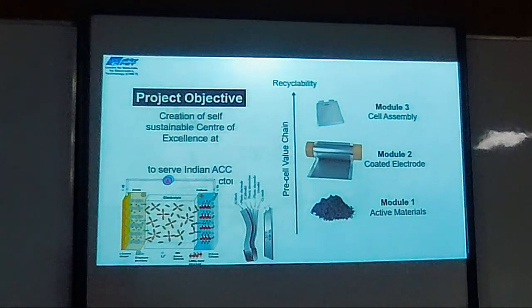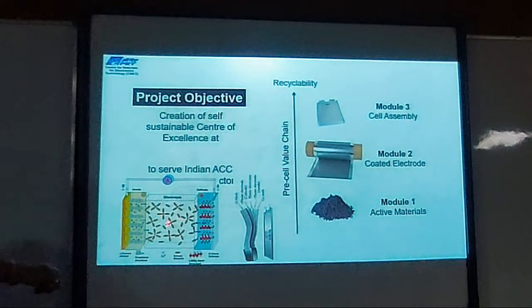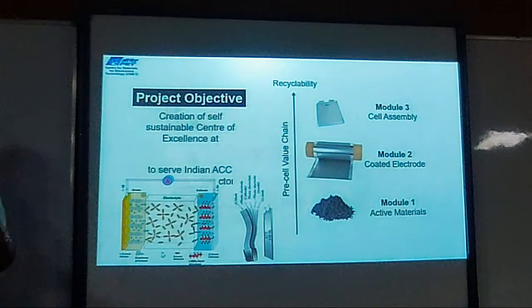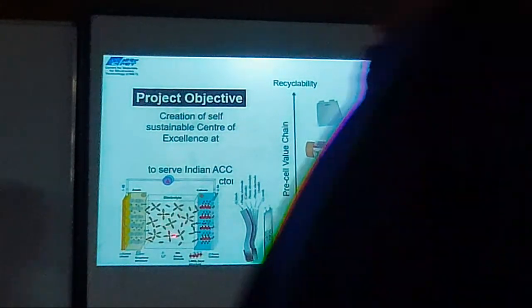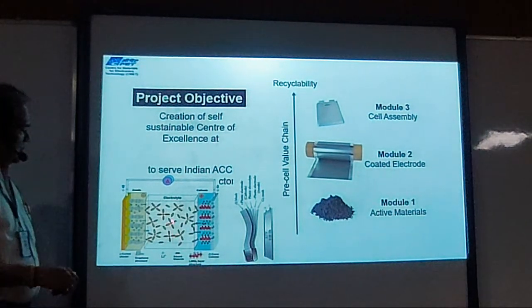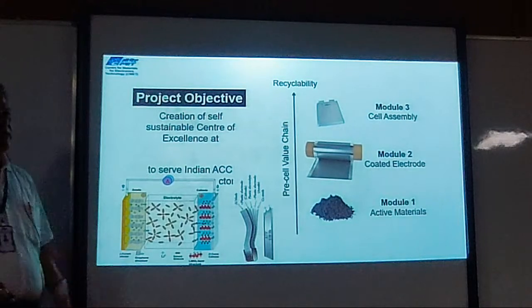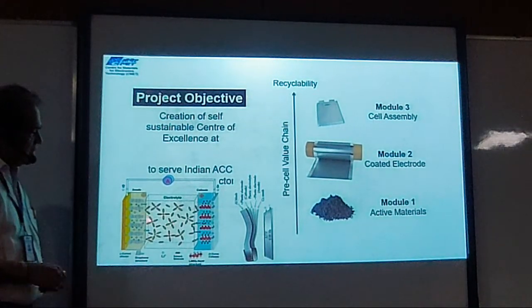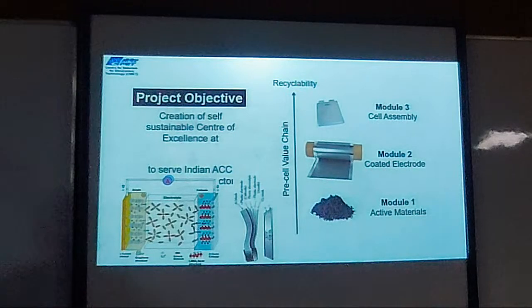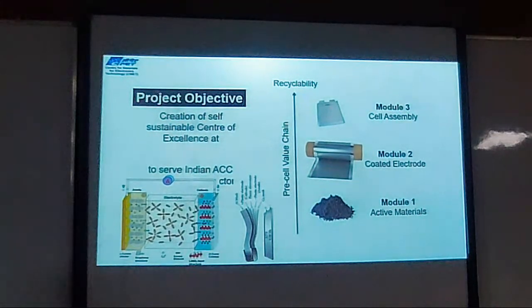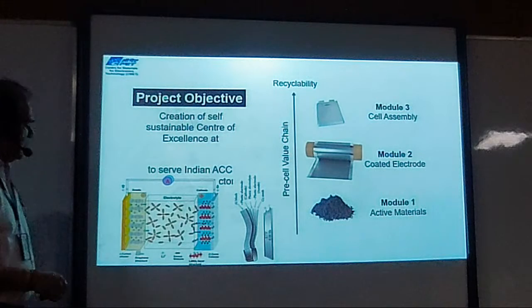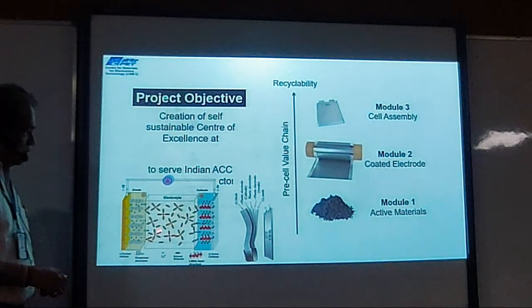Why? Because when we are transporting ions, they should safely reach the anode or safely reach the cathode. They should not react in between. As soon as they start reacting in between, their reversibility goes down, meaning your charging and discharging will come down, right? So you should have a very safe electrolyte. The ionic conductivity of the electrolyte is almost of the order of 10⁻³, so the conductivity is much better. The current problem is that these electrolytes are organic based. Lithium and sodium get dissolved in the electrolyte, an organic solvent like dimethyl carbonate, ethyl carbonate, and we put in a one molar solution.